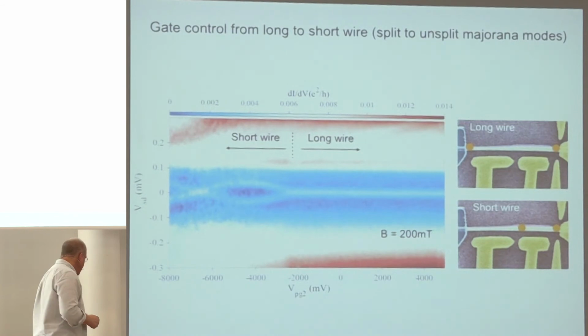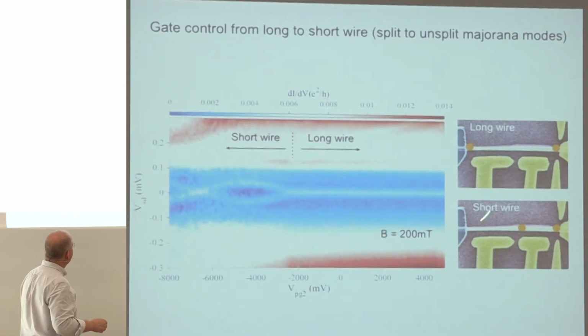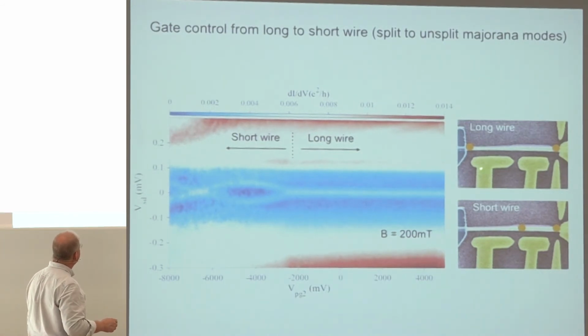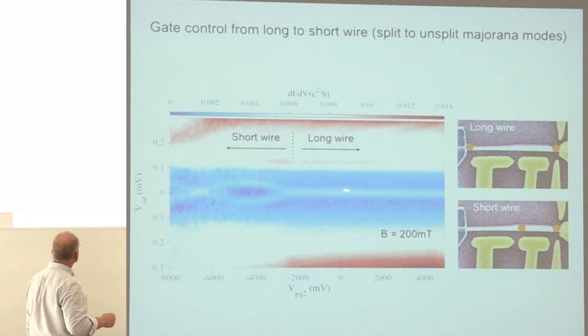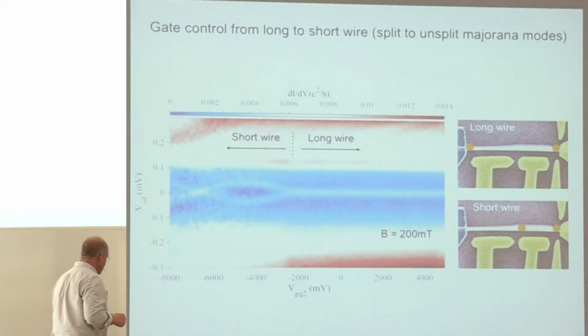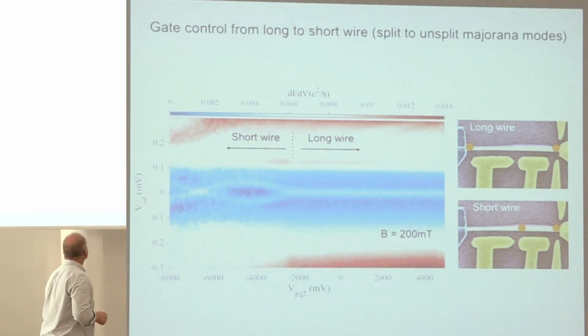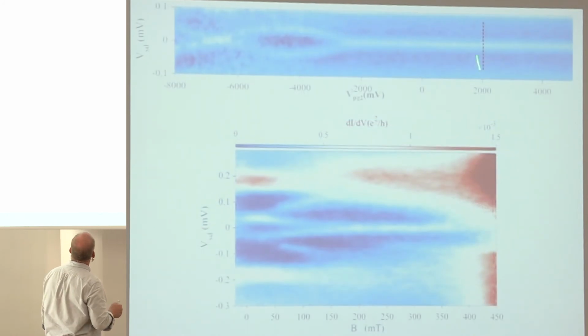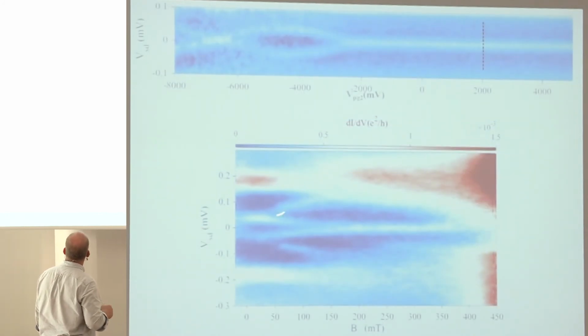Now you can say, as a function of that magnetic field and as a function of that gate voltage, when the gate voltage is 0 or positive, it's a long wire. When it becomes negative, it's a short wire. I can look at 200 millitesla, which is where they cross, and I can see that there's a zero bias peak until it becomes a short wire, and then they split and begin to oscillate as you move past that point. And you can look at any one of those values and see, for instance, up here at +2 volts, what the system looks like.